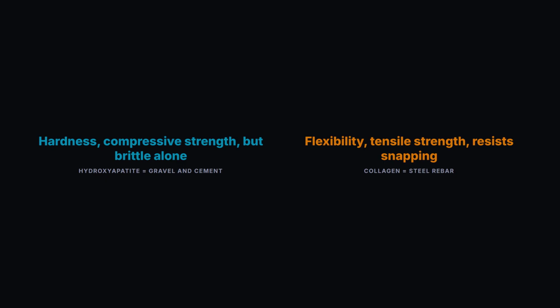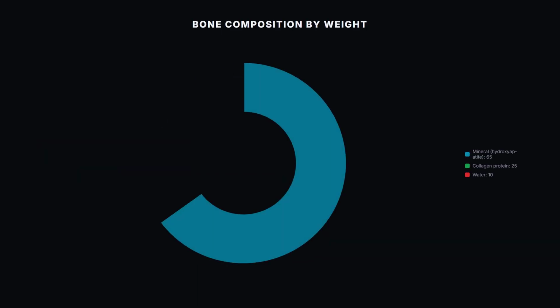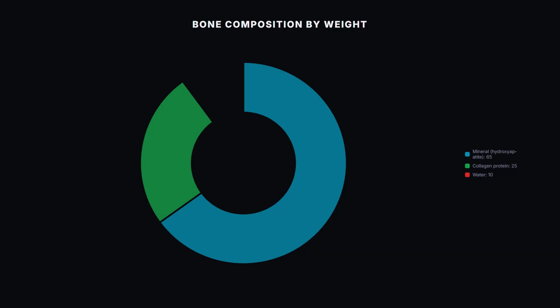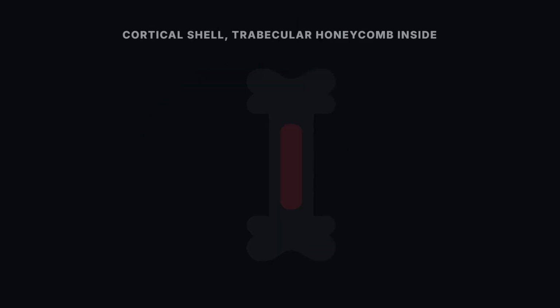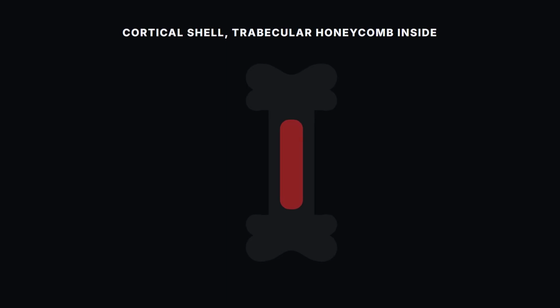By weight, a typical adult bone breaks down to roughly 65% mineral, about 25% collagen protein, and the remaining 10% water, woven through the structure at a nanoscale level so intimately that you can't actually separate the two components without destroying the material's properties. This composite structure isn't uniform throughout a bone, either. The dense outer shell, called cortical bone, is where most of this mineral collagen composite does its heavy lifting. Inside, a honeycomb-like lattice called trabecular bone adds strength, while keeping the whole structure lightweight enough for you to move around.